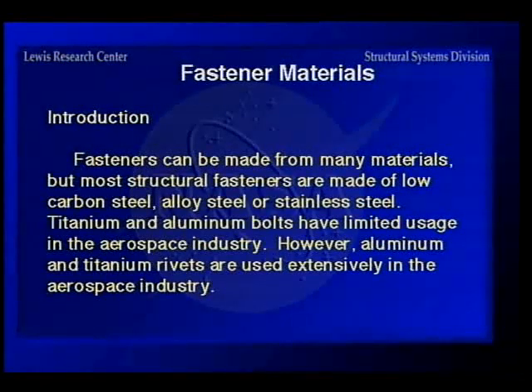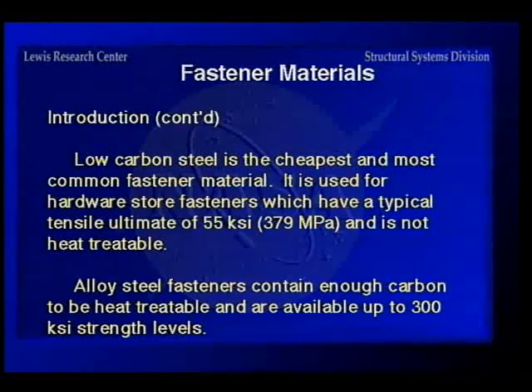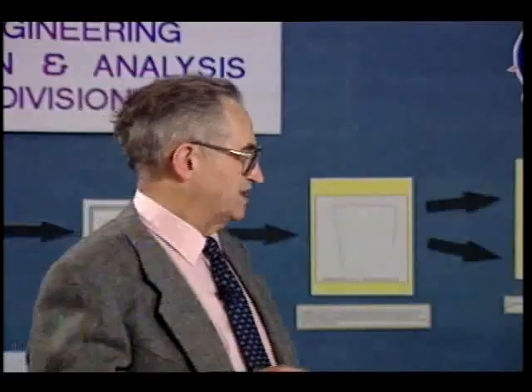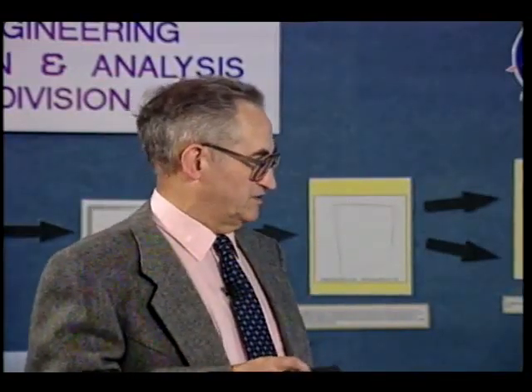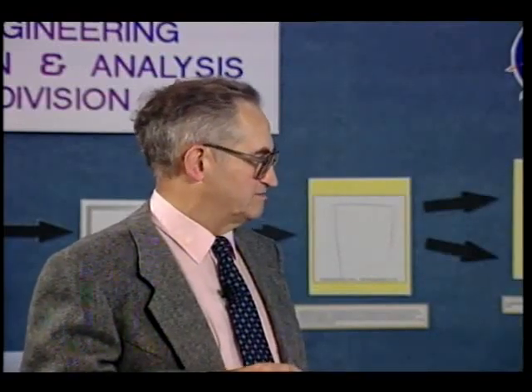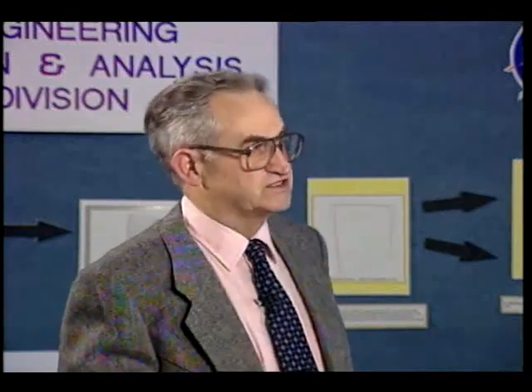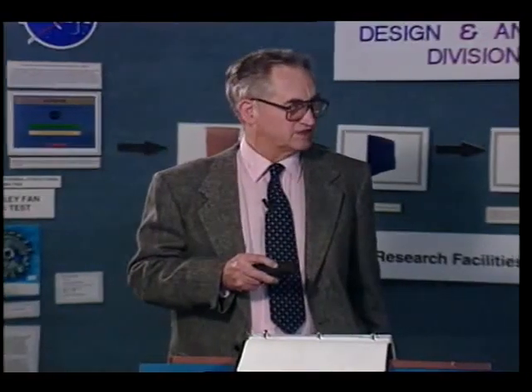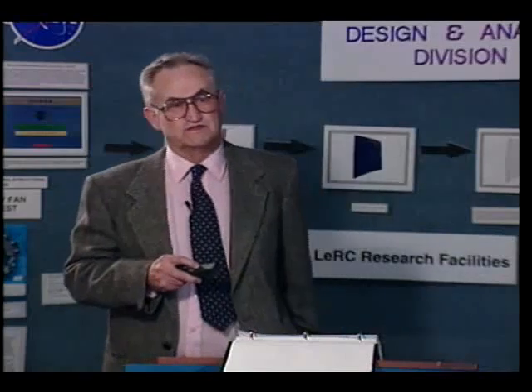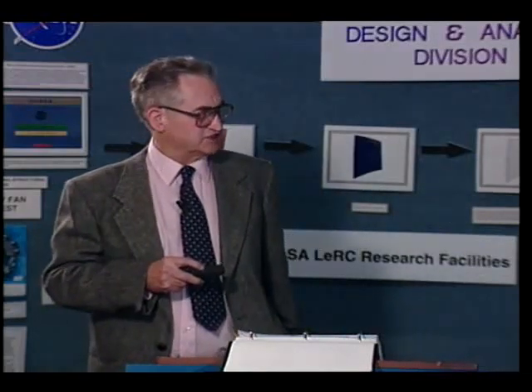Now, fasteners can be made from many materials, but most of them that we're familiar with are made out of steel. The hardware store type are made out of what's called low-carbon steel, then the alloy steel for the grades 5s and 8s that we use around here in the socket head cap screw. Titanium and aluminum bolts have limited usage in the aerospace industry, but on the other hand, aluminum and titanium are used a lot on the aircraft design, particularly since you have aluminum skins on most airplanes, and you want the rivets to be of the same material because of the differential temperature giving you problems on expansion and contraction.